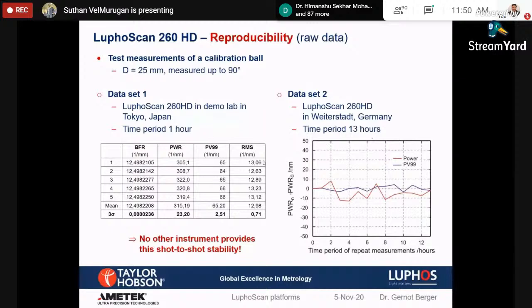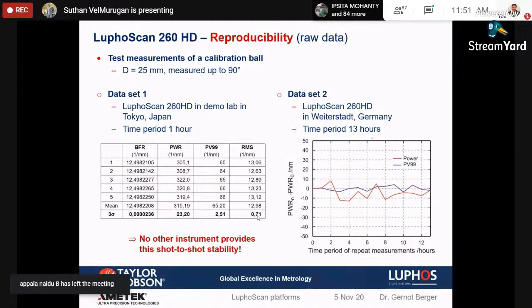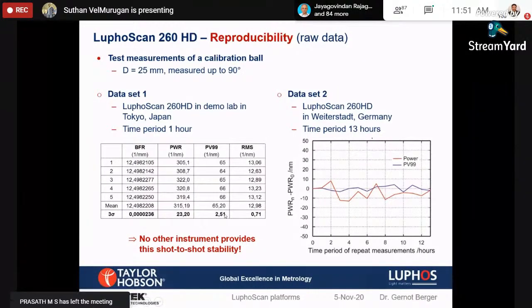And I have some statistical data on how accurately we can measure. We had a 25 millimeter diameter test calibrated sample, which was calibrated in an internationally traceable laboratory, the US laboratory. We tested almost 5 times: take the part, put it back, and measure it. You can see the difference of the 5 measurements is just 0.7 nanometer RMS, which is less than 1 nanometer. And the PV, these are the parameters which customers are mostly into, PV 99 and power. PV 99 is a very tricky parameter. All the customers measure it. For all 5 measurements, the result is less than 3 nanometers.